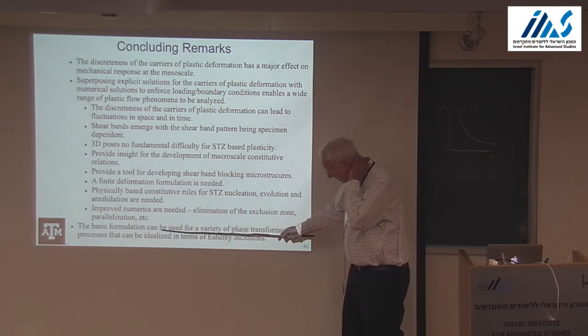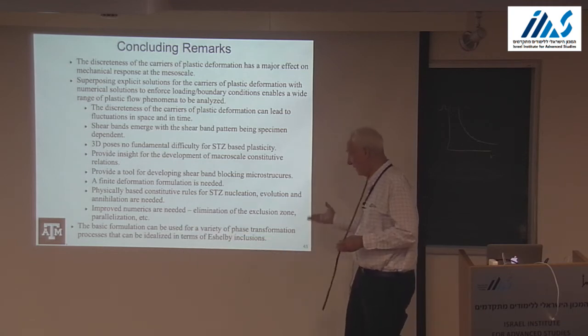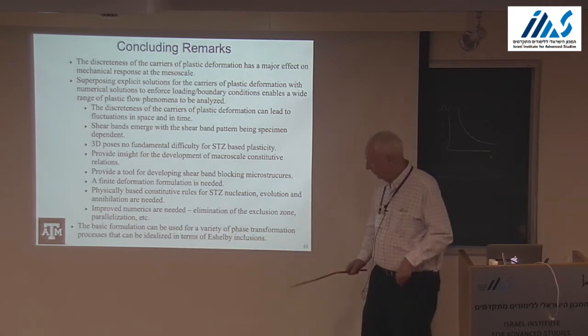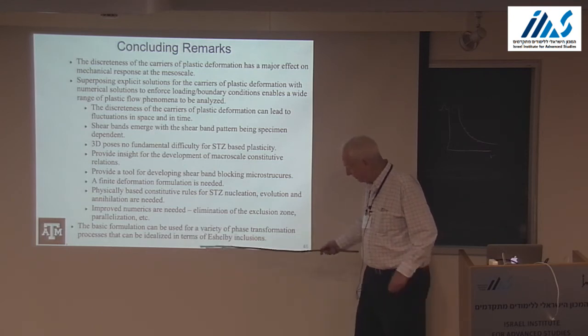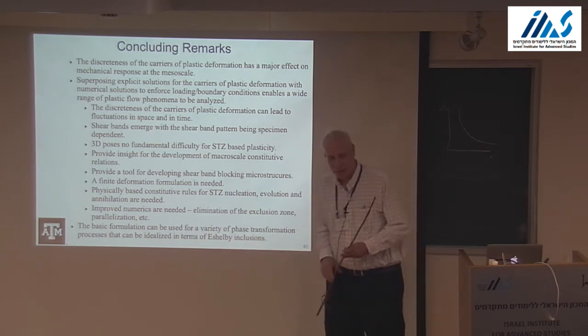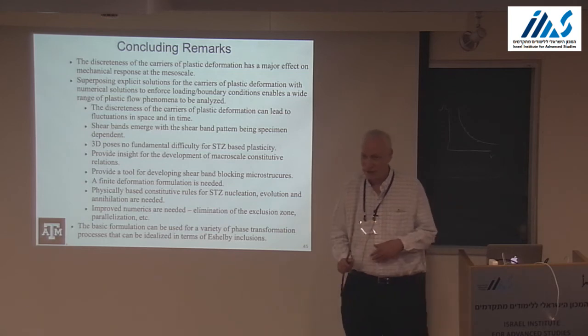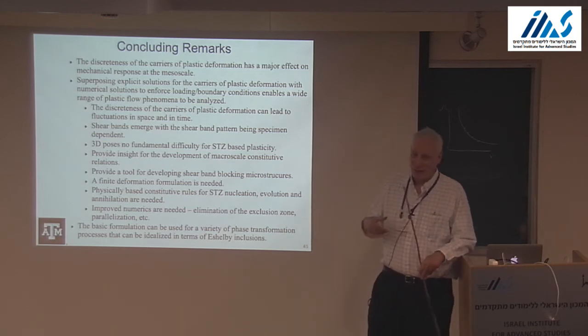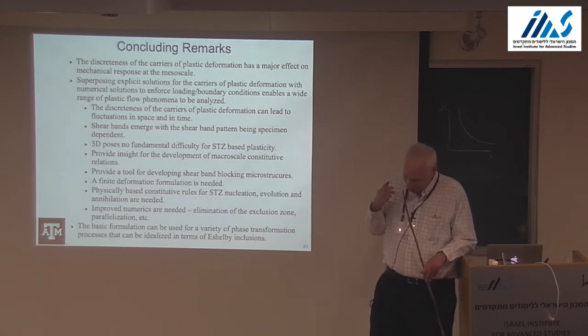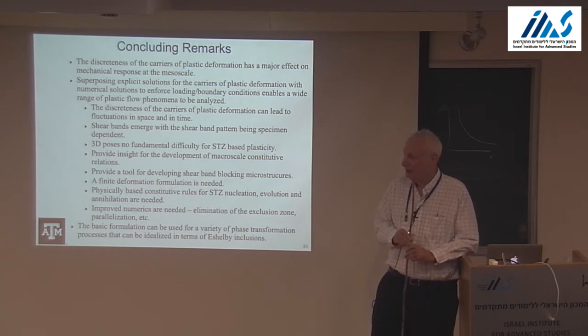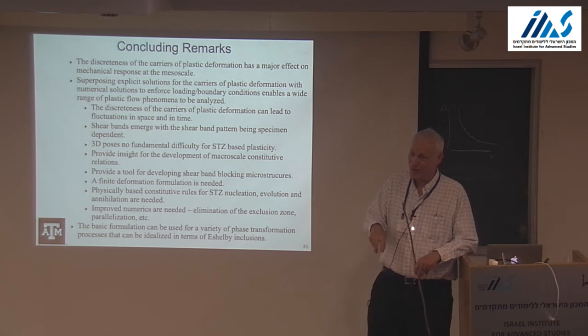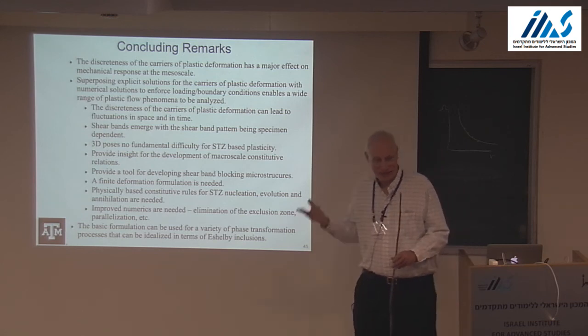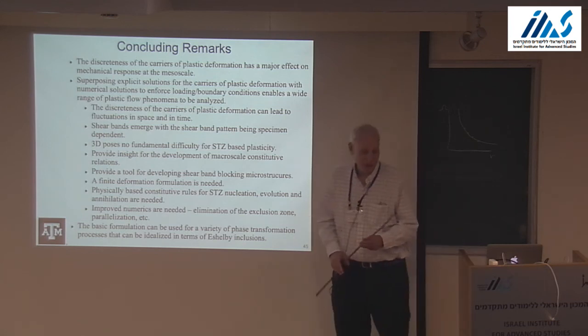Another thing is, I think this basic formulation can be used for a variety of phase transformations, where the phase transformation can be idealized in terms of an Eshelby inclusion. For example, some smart materials. Some people believe that high entropy alloys deform by both dislocations and STZs. So this provides a tool for that as well.